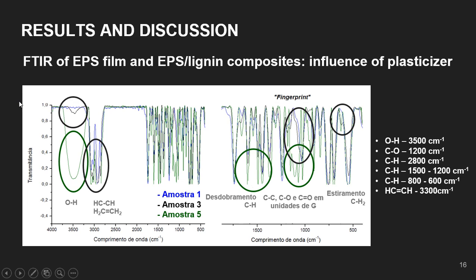Analyzing the spectrum of sample 5, a more prominent unfolding of the band of the hydroxyl at 3,500 is circled in green, as well as the carbon and oxygen connections at approximately 1,200 cm. In addition to widening the splitting bands of hydrocarbon bonds at approximately 1,500, such results may indicate that the insertion of polyethylene glycol in the film's composition causes an increase in the space between the molecules, thus increasing the vibration energy absorption of the composites.